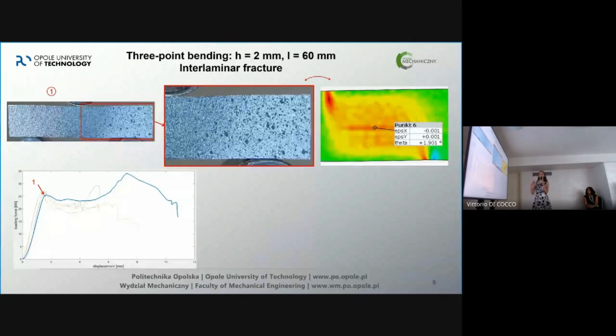And on this specimen as well, we can't see any information that we're going to have a catastrophe in a moment. But it happened because, as you can see, there was a drop, not so big, not as in the previous version, but also we can see that there was a lowered volume. But what's interesting, the force started to grow up. But the reason is very easy. Instead of shearing, we started to have compression here. But after that, something like this happens.